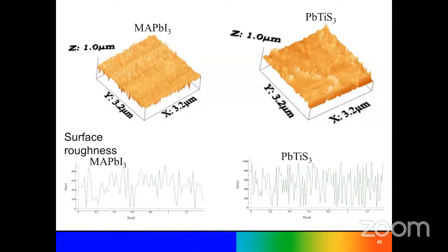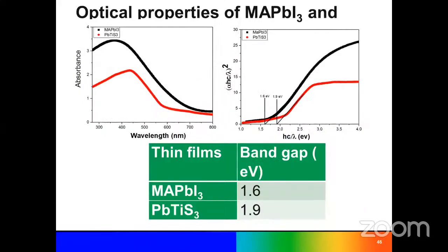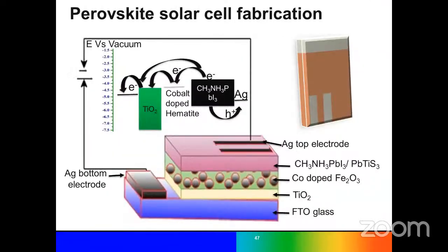Then we did AFM analysis for getting the surface analysis. Finally, from optical analysis we got the band gap value around 1.6 eV in the case of methylammonium lead iodide, which is close to the reported value. So if you see these things, this photoanode may also be used for solar cells.